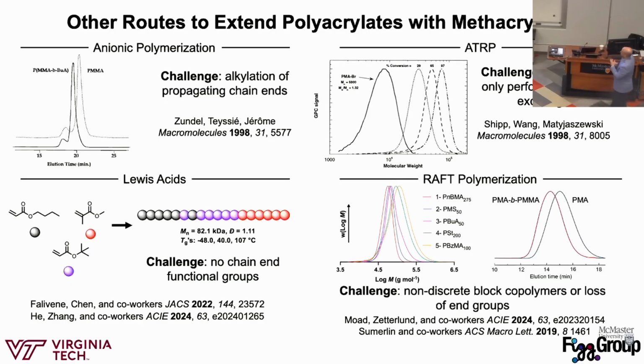If we look more recently, you can make these sorts of acrylic, methacrylic block copolymers using Lewis acid catalysis. This was developed by Eugene Chen at Colorado State, where you can just mix these monomers together, and then according to the Lewis acid that you're using and their reactivity ratios, you can get these pretty well-defined multi-block copolymers. And the nice thing is that you can just mix all the monomers together and just according to the reactivity ratios, you'll get this block copolymer.